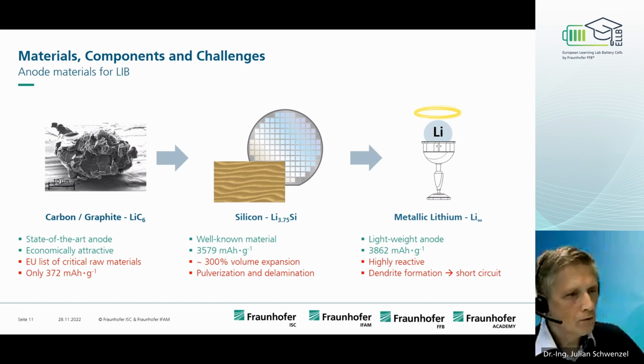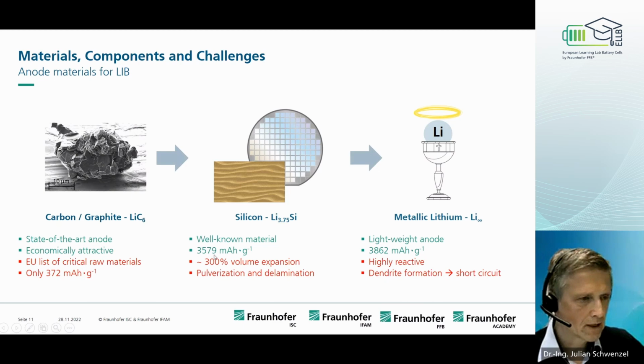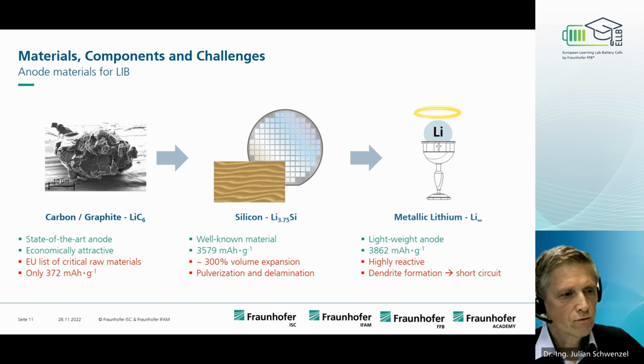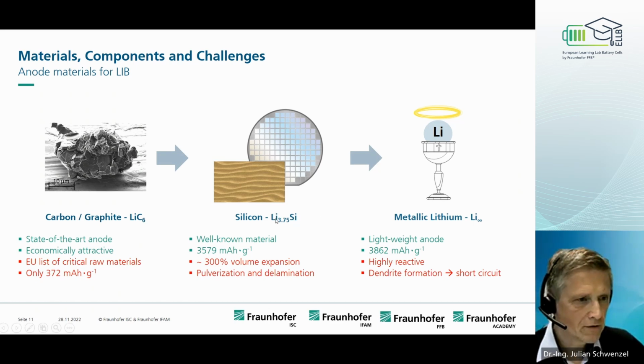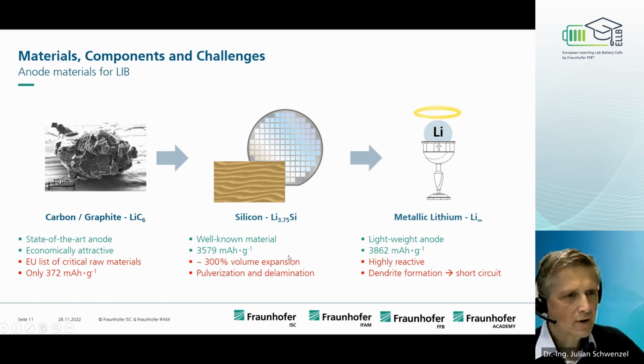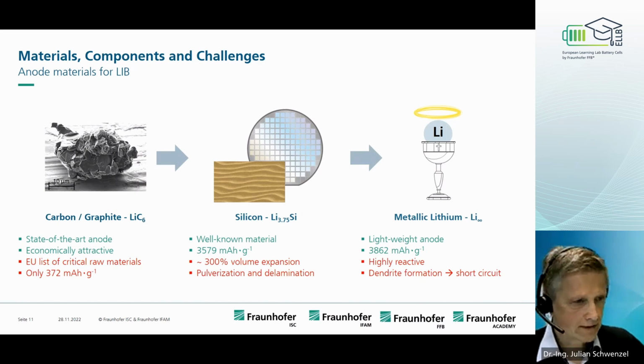There are also some developments starting. So the state of the art is graphite. Graphite is economically attractive, but also a critical material. So the idea in development is to exchange the graphite for silicon. Silicon is a well-known material with a huge capacity, similar to lithium metal, but it also shows a very high volume expansion, which means if you charge the system, the silicon reacts with lithium, and so we have a high volume change, which will also be critical for lifetime or cycle stability.